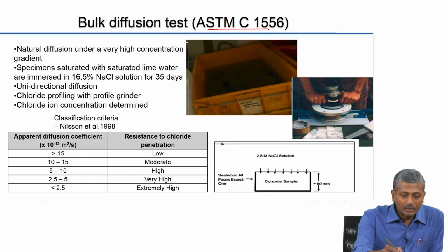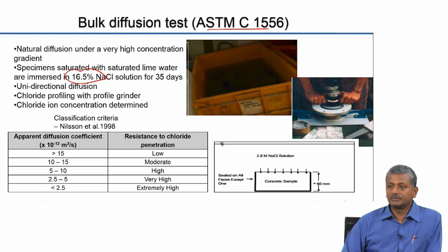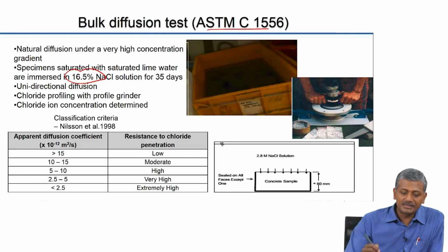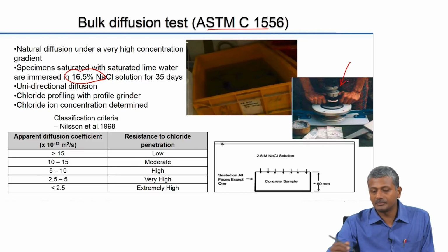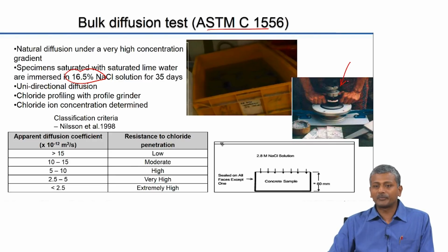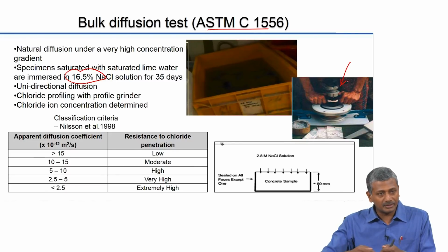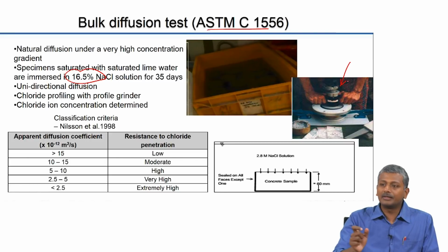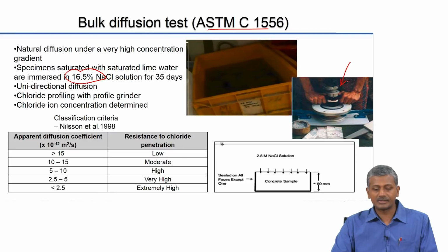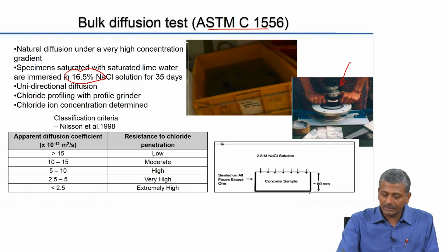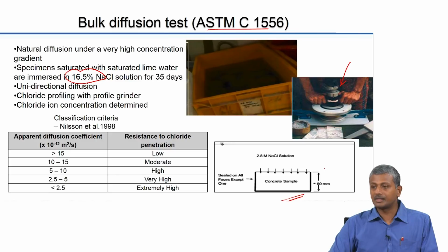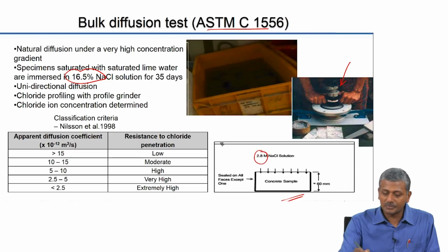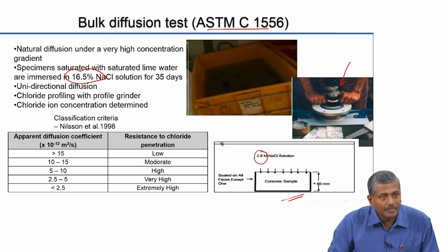Okay, so here you have 16.5% sodium chloride solution is what is used. And chloride profiling is done with a profile grinder, what is shown on this side here. Or you can even have a more workshop oriented process like a lathe. You can use a lathe to section off the concrete layer by layer and then determine the extent of chlorides inside. Okay. So again, this is a schematic which is showing the cylindrical concrete sample sitting inside a tub of sodium chloride solution. Of course, here it's presented in terms of molarity, 2.8 molar, that corresponds to about 16.5% sodium chloride.